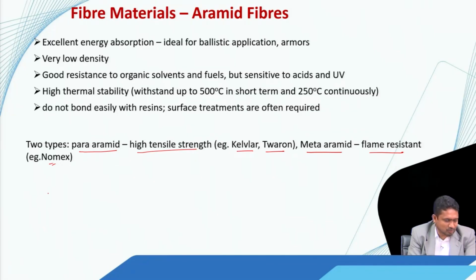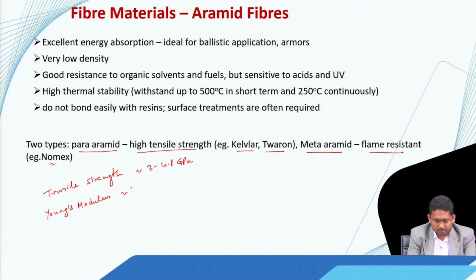Now if we look at their properties, tensile strength is around 3 to 4.1 GPa, and Young's modulus is 70 to 130 GPa. Density is 1.44 gram per cc, and they have excellent fatigue resistance.